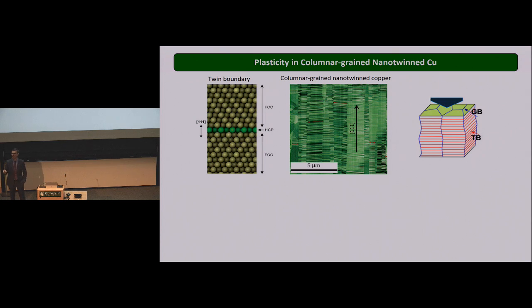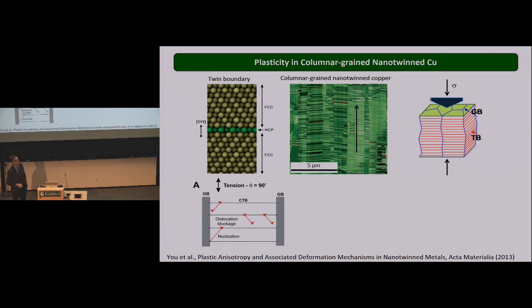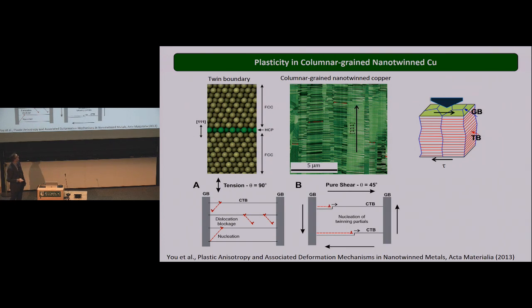Mechanically, they are very interesting because we can isolate the mechanism by simply changing the orientation of the loading direction. For instance, if I compress or apply a nanoindentation to the film, in this case, I will nucleate dislocation that will be blocked by the interface. Now, if I shear the film in some way, we create those dislocation that create some detwinning that cause the softening we saw in the previous slide.